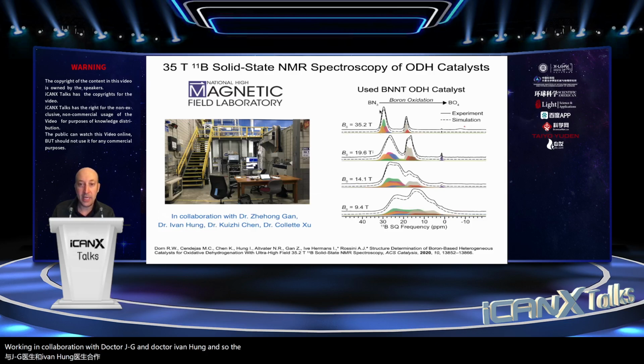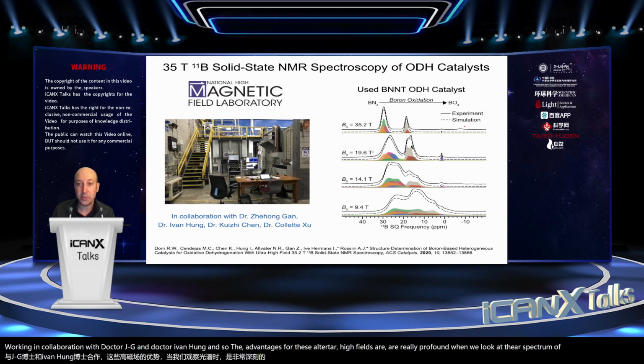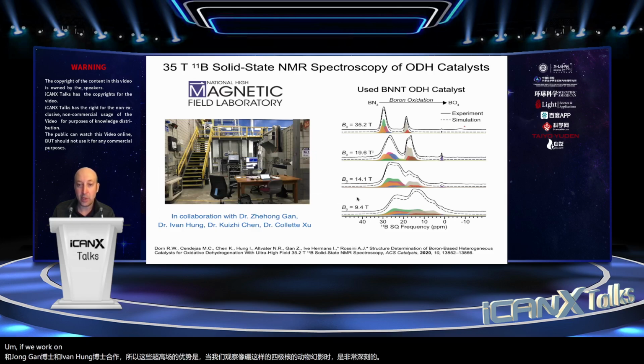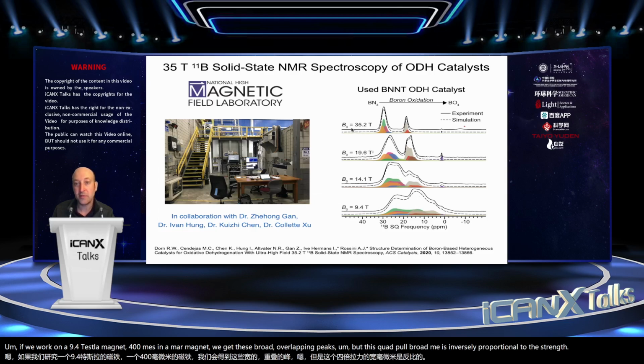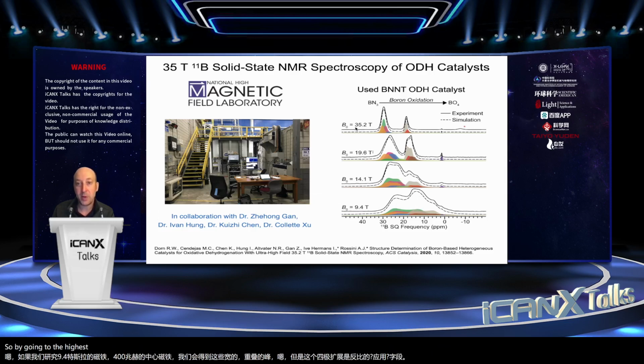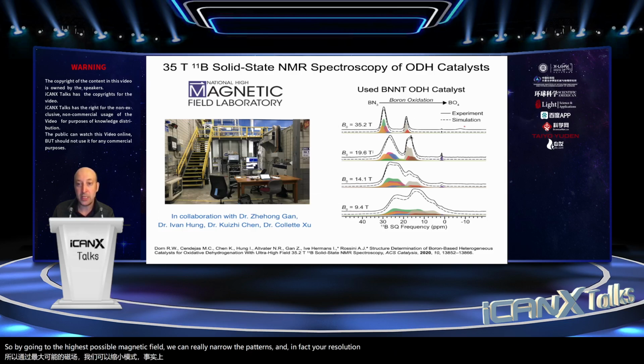And so the advantages for these ultra high fields are really profound when we look at the NMR spectra of quadrupolar nuclei like boron. If we work on a 9.4 Tesla magnet, 400 megahertz NMR magnet, we get these broad overlapping peaks. But this quadrupolar broadening is inversely proportional to the strength of the applied field. So by going to the highest possible magnetic field, we can really narrow the patterns. And in fact, your resolution in your 1D spectrum is going with the square of the applied magnetic field. So that's how we can get these dramatic reductions in line width and really great improvements in resolution.